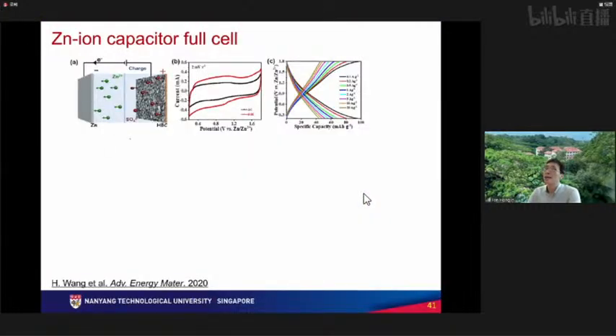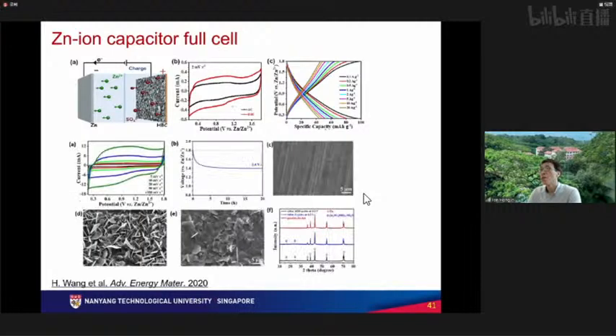The working mechanism is actually quite simple. We just borrow the mechanism from lithium and sodium ion capacitors. Zinc has a dissolution and redeposition on this side. Positive ions go to this side, and the anions go to the other side. So it's a dual-ion process. Compared to carbon black, I find there's a little bit of dendrites, but not so serious. This is ZHS, zinc hydroxide sulfate flakes, right?